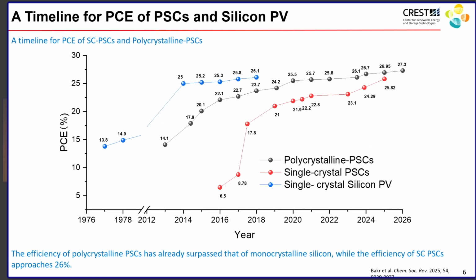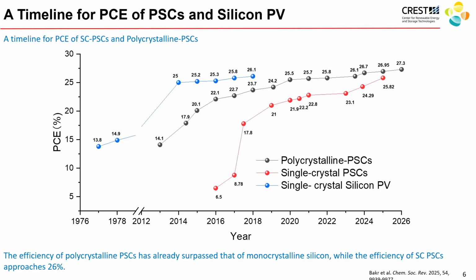So in the last 17 years, perovskites have gone from about 3% efficiency all the way to 27%, and that took silicon about 60 years to achieve this kind of efficiency. And there are multiple types of perovskite devices. There are polycrystalline devices and there are single crystal devices, and each one of them is going through a different transformation.